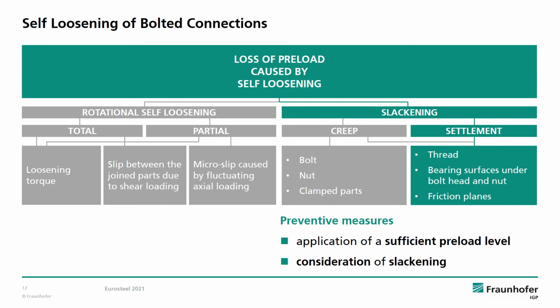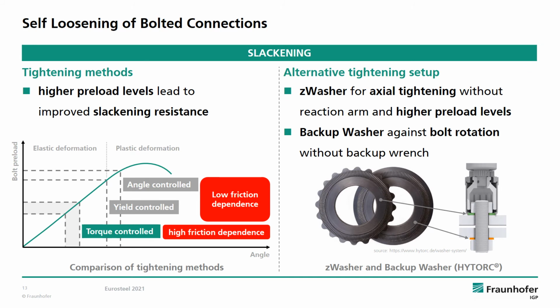Another reason for self-loosening is slackening. Slackening can be caused by creep of the connection components or by settlement. Preventive measures are the application of a sufficient amount of bolt preload and to consider settlement effects. The level of bolt preload applied is highly dependent on the tightening method chosen. With torque-controlled tightening, a bolt preload is typically the lowest and friction dependence is high. This is the way our boat landing bolts have been tightened.